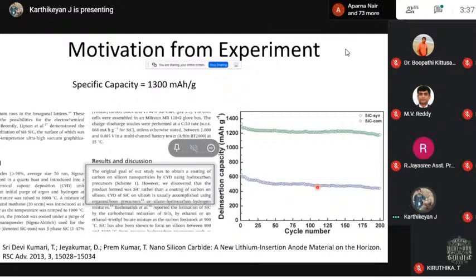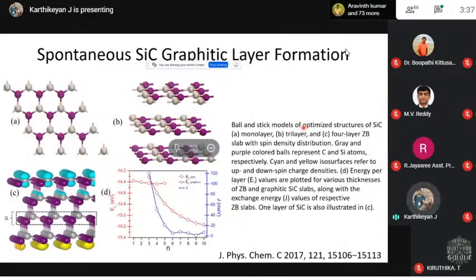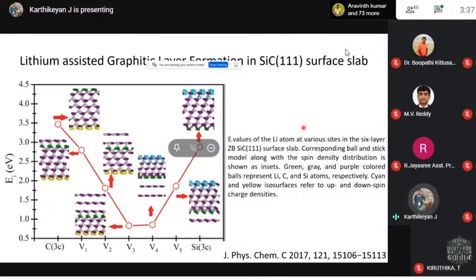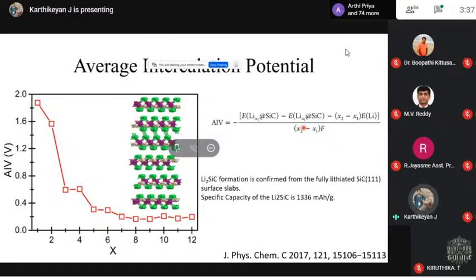But when they reduced the size, they could achieve a really high capacity. So the high capacity comes because all these silicon carbide layers are forming graphitic structures, and that gives a very high capacity, and that capacity is also matching with our models. So that's a finding from DFT. So it really gives me a pleasure that DFT is a very powerful tool to understand at the atomic level what is happening inside